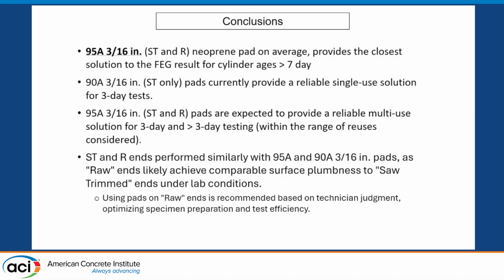And so the conclusions that we came to were: the 95A 3/16 pad for saw trim and raw end cylinders, on average, provides the closest solution to the fixed and grinded condition for cylinders greater than 7 days. We found that the 90A 3/16 pad for the saw trim cylinders only provides a reliable single-use solution for 3-day tests, so very, very early age tests. And we found that the 95A 3/16 pad for the saw trim and raw end could be used as a multi-use solution for very early age tests and later age tests. Overall, for the saw trim and the raw end cylinders, the 95A and the 90A 3/16 pads achieved very, very similar results.